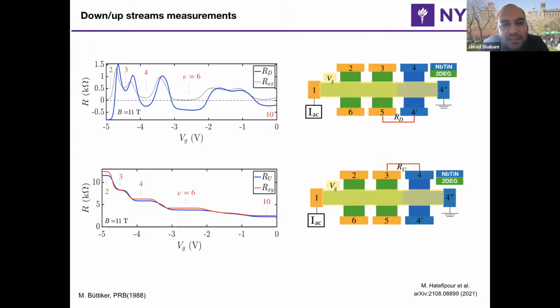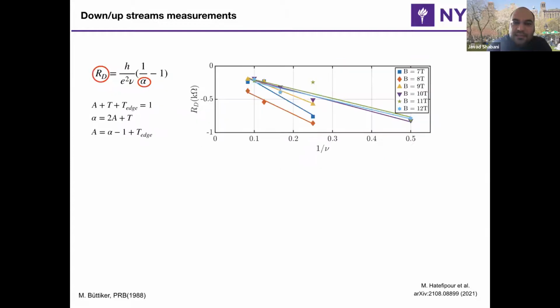So we looked at the upstream data, which would be pin numbers 3 and 4 in this graph, if you look at the bottom graphs. And you would see that the Hall data starts to deviate from what the normal RXY is. The normal RXY is shown in the bottom graph in red. The upstream is blue. Now the upstream value is lower than the Hall data, as if now the Andreev reflection is not contributing to the Hall data. And that indeed is consistent with this picture of Büttiker, that basically ideally you want to see a very large negative resistance in downstream and half of the conductance of the Hall data, right?